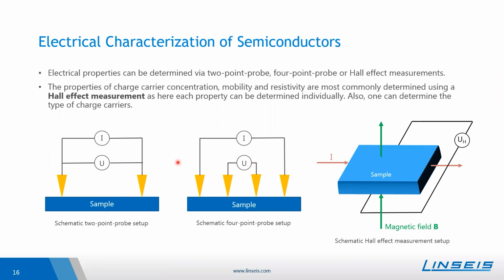However, in most cases, one finds out the electrical properties using a Hall effect measurement setup. This brings the advantage that the charge carrier concentration, the mobility, and the resistivity can each be determined individually and not as a product as with the 4-point probe setup. So then one has all single properties individually as a result. So this is the schematic Hall effect measurement setup, so that one uses more or less also a kind of 4-point probe setup, but additionally one applies a magnetic field to the sample to investigate the properties.